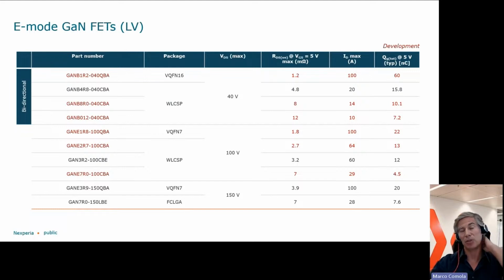The 40 volt bidirectional, just to spend more words, replaces two silicon MOSFETs back to back for, let me say, over current protection or over voltage protection for a load switch, and so you increase the power density using just one device instead of two. The 100 volt and 150 volt can easily replace the low voltage MOSFET, just introducing the benefit of using gallium nitride, so higher power density, and then the possibility to work at high frequency and high efficiency.